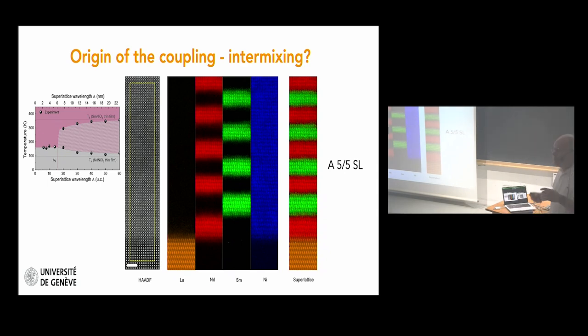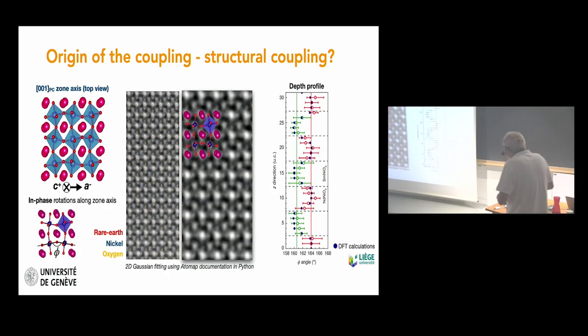The second thing, we thought it's probably linked to our distortions, which are different in the two materials, and these distortions have to couple at interfaces. So we performed advanced scanning transmission electron microscopy and DFT calculations, and again the answer was very clear, and in fact in line with what we know from other work.